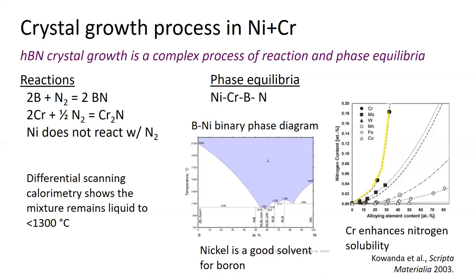I can describe it sort of simply, but there are actually a lot of things going on. There's chemical reactions going on. The boron reacts with the nitrogen to form boron nitride. The chromium reacts with nitrogen to form chromium nitride as well. You have phase equilibria, you have gas phase nitrogen and a liquid mixture of nickel, chromium, and boron. So that's kind of the setup.